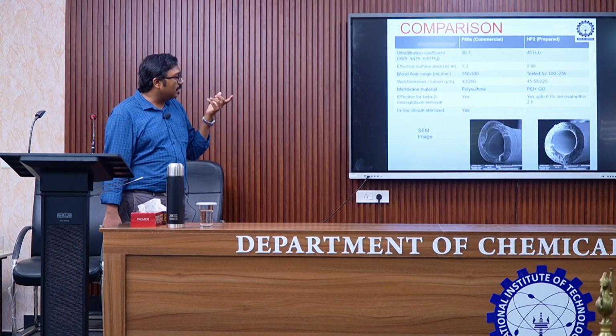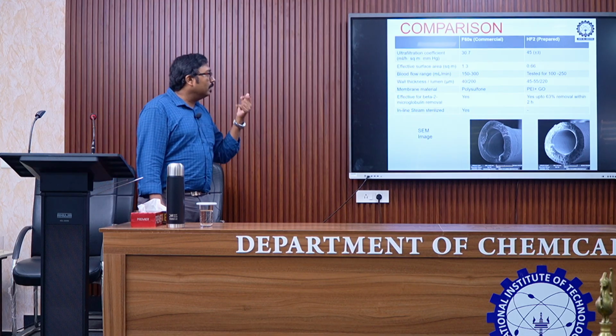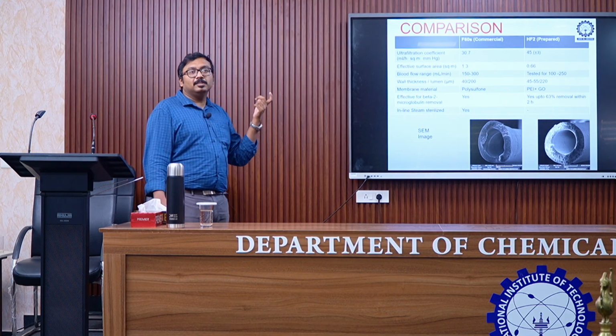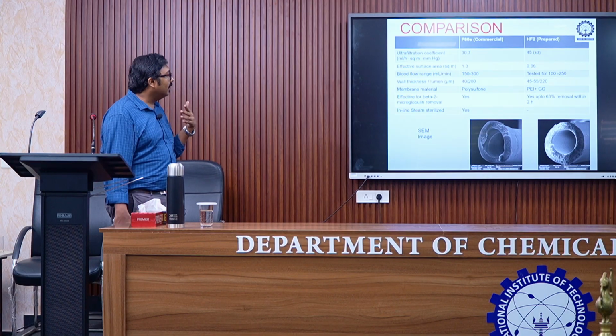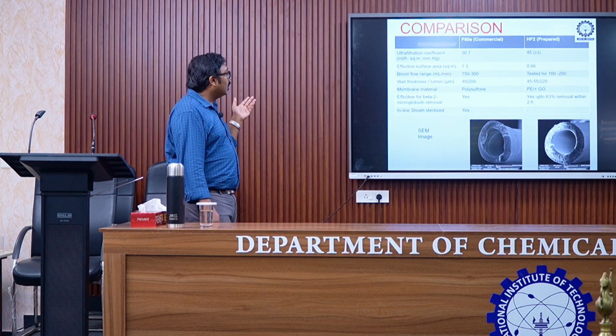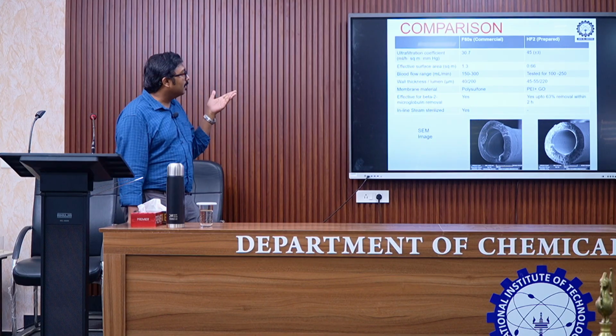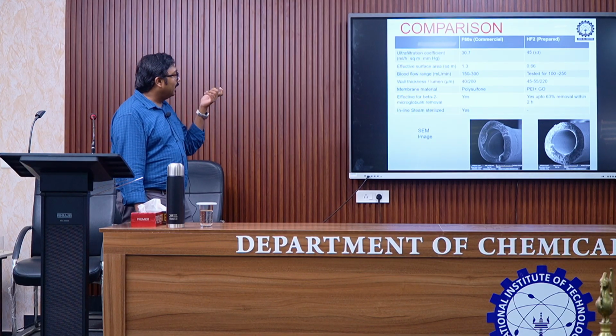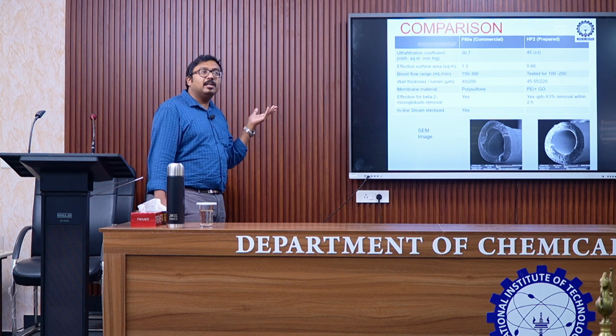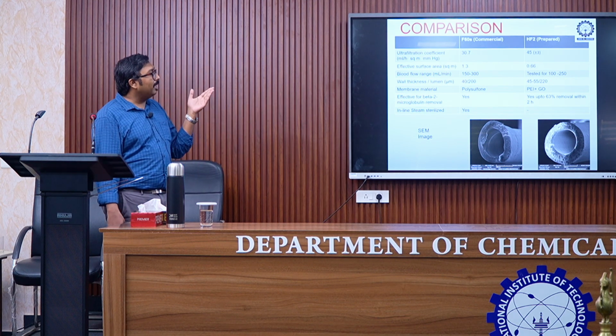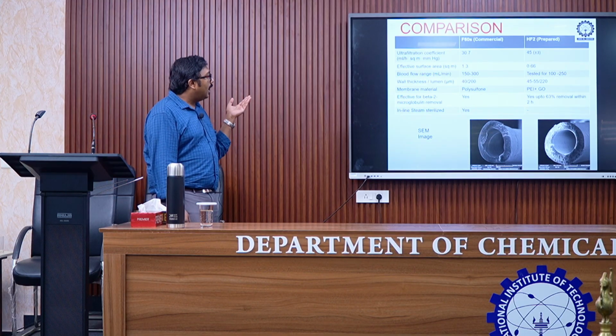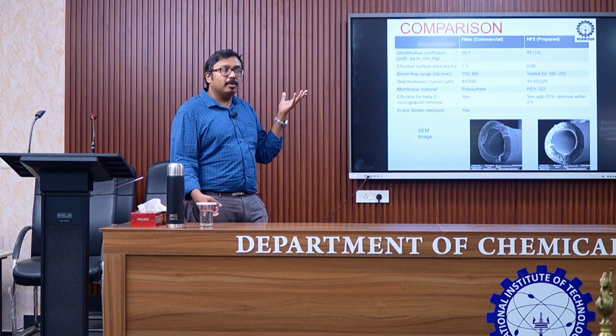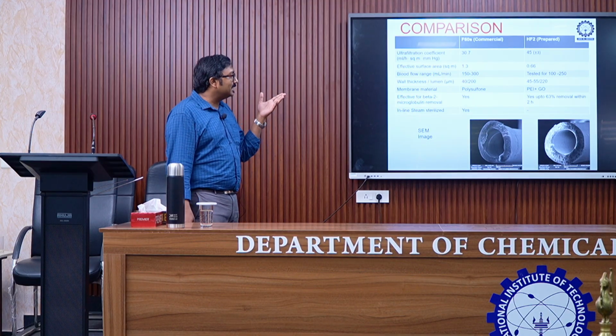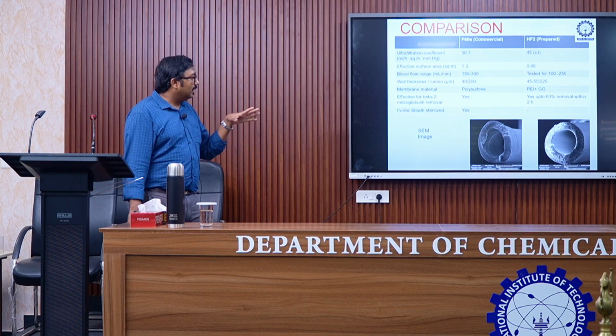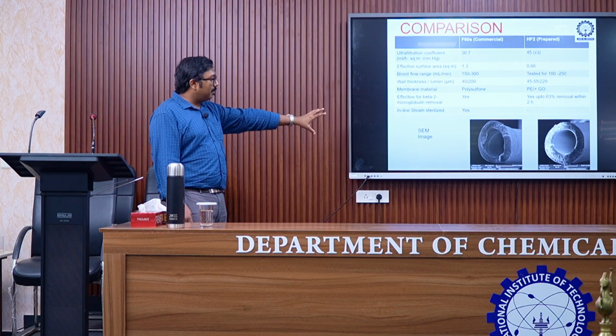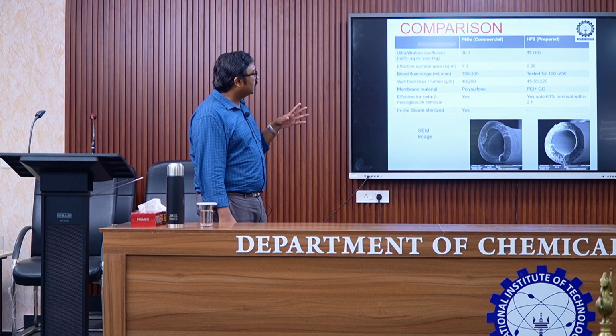The ultrafiltration coefficient was slightly higher. We were able to make only a 0.66 meter square membrane, because we had limitations in making larger area. The blood flow ranges were similar. Wall thicknesses were slightly higher than the commercial one. The membrane material in Fresenius is polysulfone, and we have used polyetherimide plus graphene oxide. For beta 2 microglobulin, a middle molecular weight solute, we could remove 63% within 2 hours. And these are the SEM images of the two membranes. So we were in line with that.